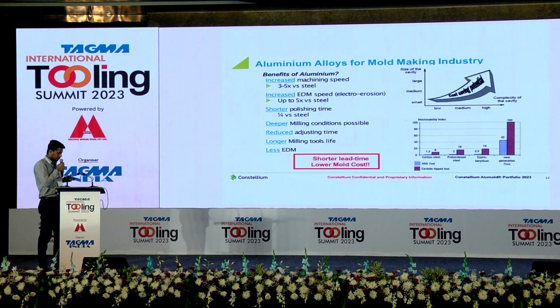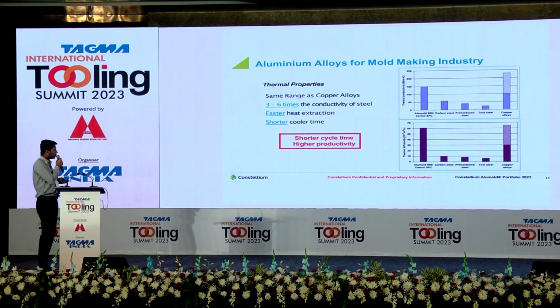Whenever the tool room manager thinks about the cost of manufacturing a tool mold, the major factor is milling cutter or milling tool life. We can increase our milling cutter or milling insert life by a minimum of 3 times when we manufacture aluminum molds. This is a typical comparison machining index showing where the aluminum alloys stand. Coming to the thermal conductivity part, we can reduce the cycle time. Believe me, we can reduce the cycle time by 30 to 50% of what is currently running in tool steel.